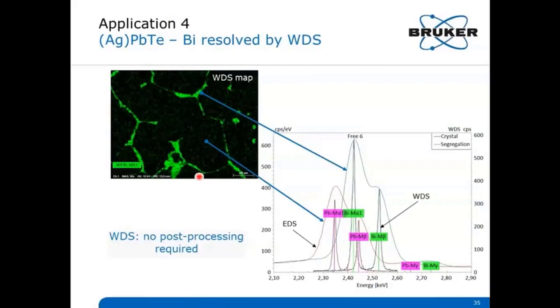WDS energy range scans acquired on the segregation zones nicely show distinct bismuth lines. Here, these are the peaks of the bismuth M lines, whereas energy range scans acquired on the crystals don't show these bismuth peaks, but distinct peaks for the lead M lines. So lead is indicated in the crystals and bismuth in the segregation zones.